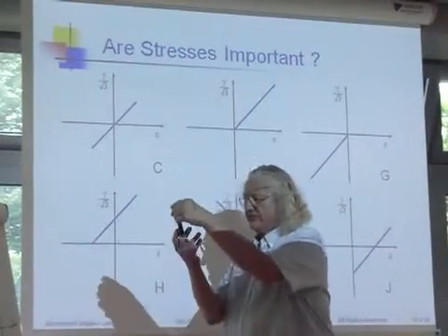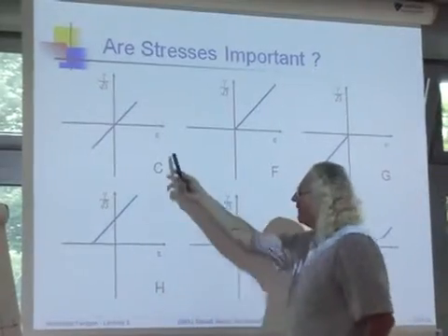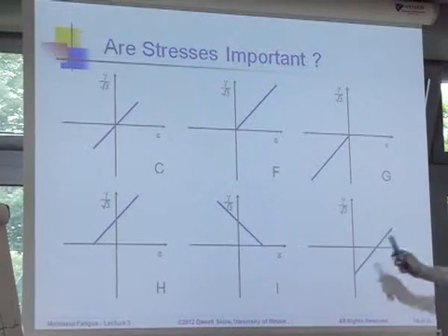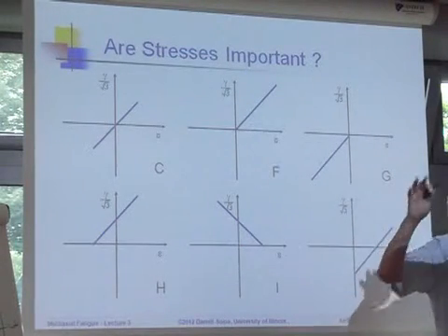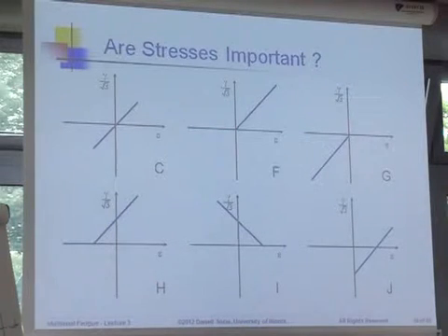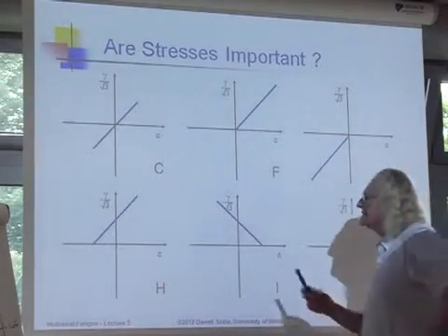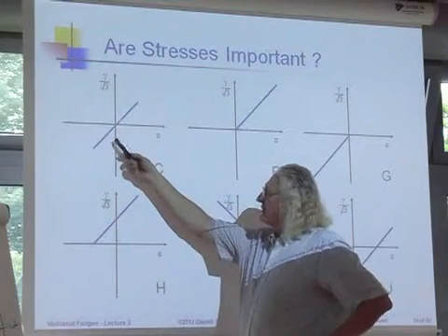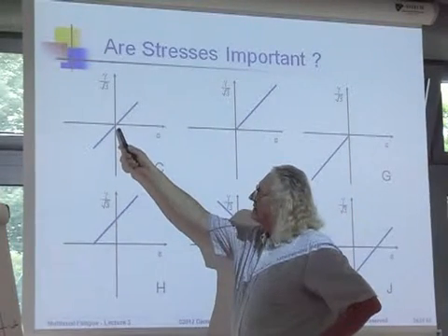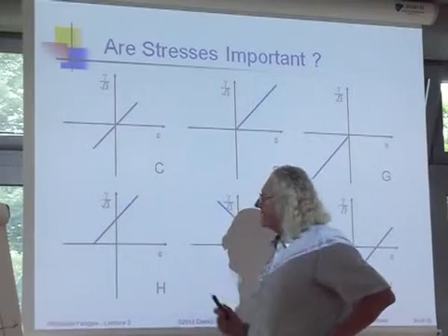Here's the axial strain and shear strain, and so this is just a test where I pull and twist. And I always keep the same range. The only thing that's happening is I'm shifting around the mean, and that shifting around the mean will shift all the different stresses that are there. So if I look at these, I have a particular life here, of course. I can choose what that is depending on the load levels. But let's just accept this as the baseline.